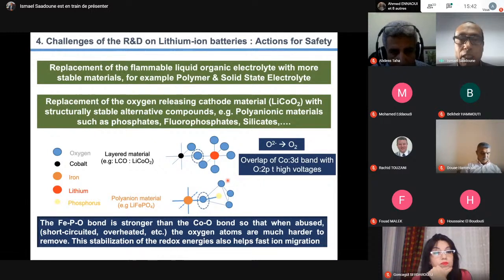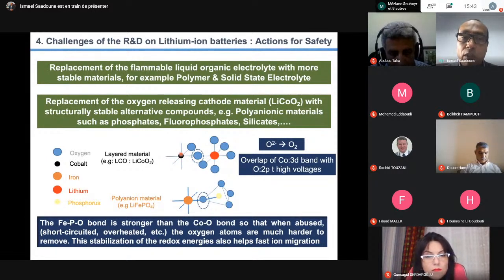I have this picture to show why we have this oxygen release. You see, this is your material, schematized. You have your lithium surrounded by oxygen, and this oxygen is shared between the lithium and the cobalt, for example. When you are charging your battery, you are oxidizing cobalt to cobalt 4+. So you have big covalency between cobalt 4+ and oxygen, and we have overlap between the cobalt 3d band and oxygen 2p band. This means that during oxidation, we are oxidizing not only cobalt, but also oxygen, generating oxygen gas that contributes to the flammability of your solvent.